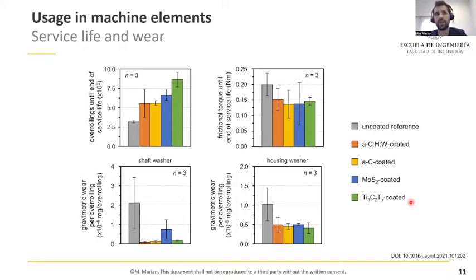This was mainly because of cage malfunction in combination with blocking balls and hot running of the bearings. So we can see that the frictional torque during the service life, during the stable operation of the bearing, of the reference bearing was somewhat higher, but the remaining solid lubricants did not really show much difference, especially given the scatter. However, we were able to see that the difference in the service life, which is defined as the number of overrolls in which the bearing can be used, was much more pronounced.